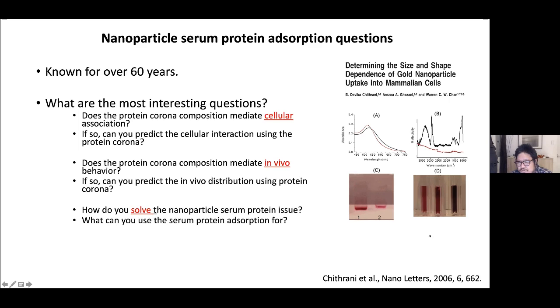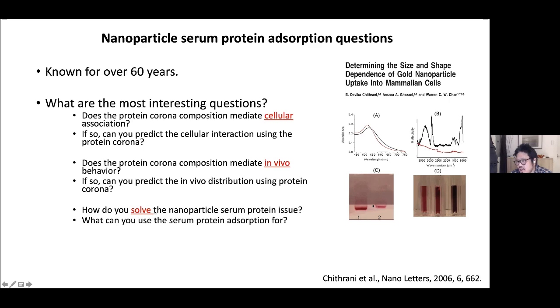In 2006, we published a study showing that the size and shape of nanoparticles affects how much they are taken up by mammalian cells. We explained this using data showing that gold nanoparticles adsorb serum proteins—demonstrated by IR spectra shifts, changes in gel electrophoresis of gold nanoparticles, and changes in surface chemistry upon serum exposure. In 2006, when we published this paper, we attributed the size- and shape-dependent interaction of nanoparticles with mammalian cells to serum proteins, though at that time we didn't know what specific protein was involved.